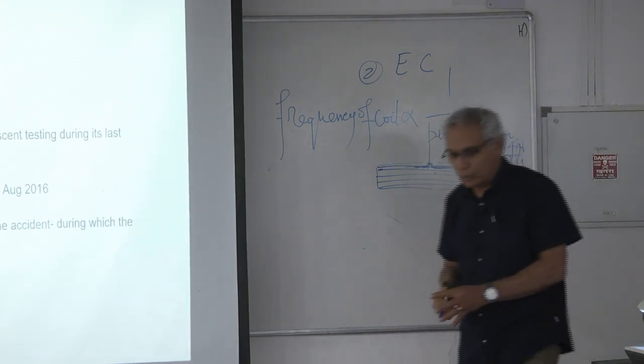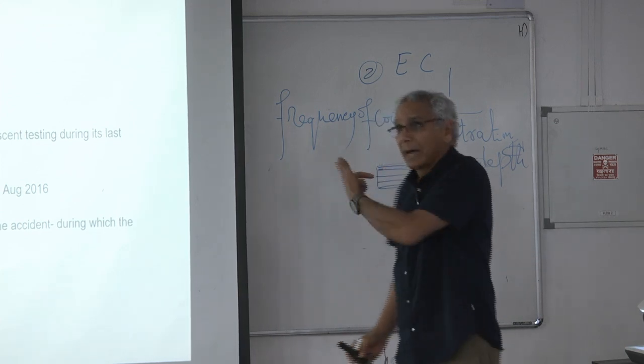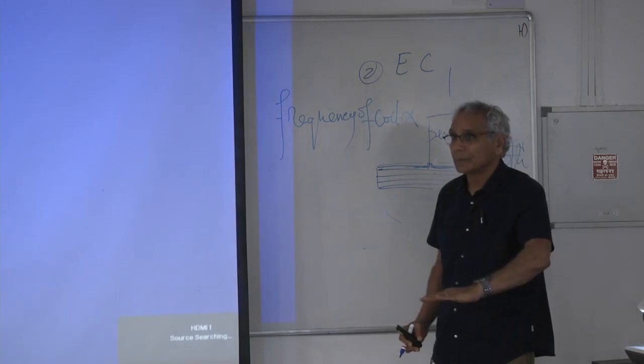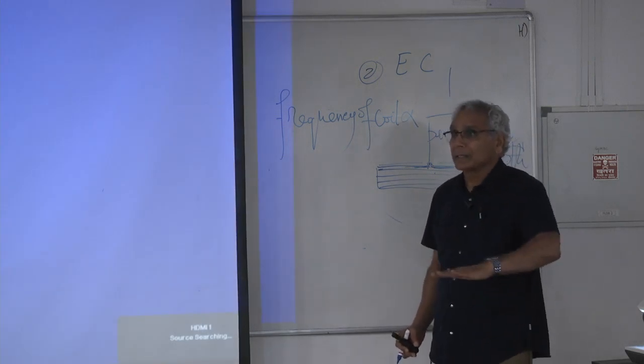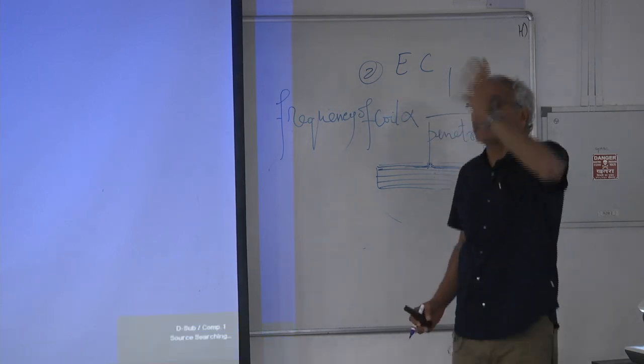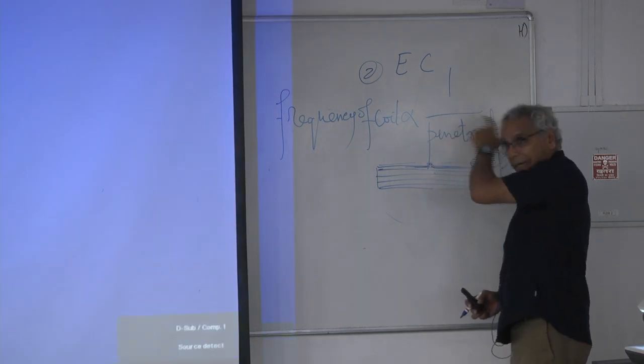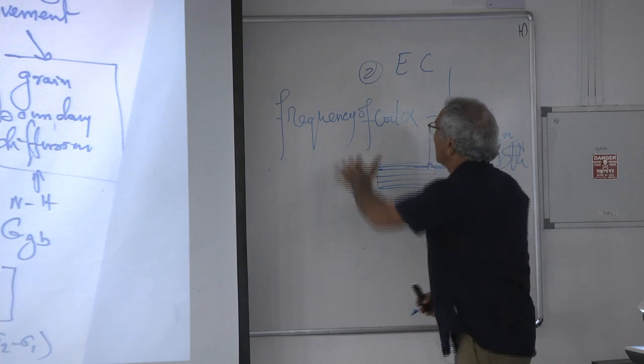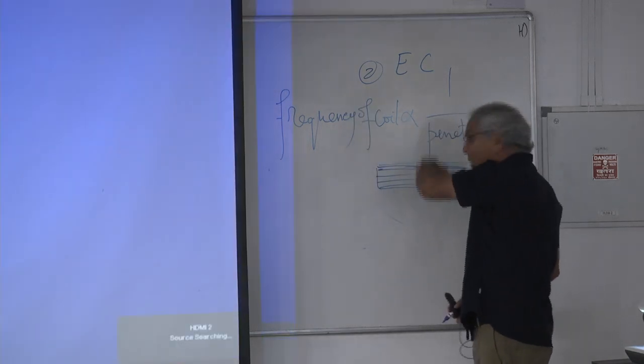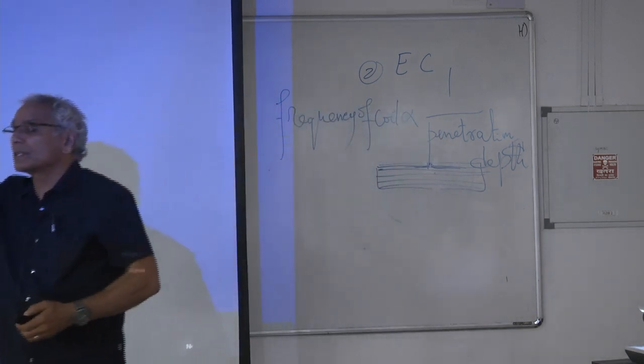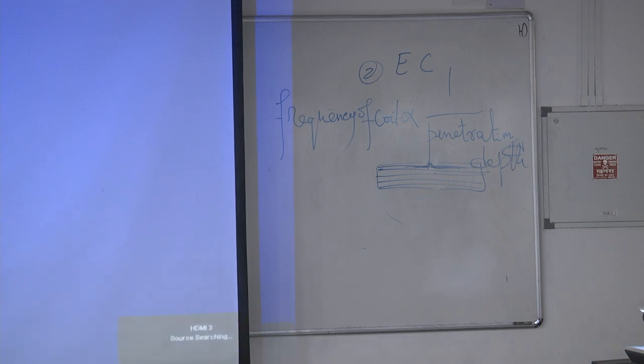If I'm looking for a crack on the surface, I use a high frequency because the penetration depth is low. So it becomes very sensitive at high frequency, and it will detect the crack on the surface. But if I want to go deeper, I reduce the frequency, and the electric field will go deeper. So the penetration depth is inverse of the frequency. The first thing you want to do with eddy current inspection is always use a low frequency coil and take a look at the forest from the helicopter, instead of looking at each tree. Then you increase the frequency and start looking at the flaws, because fatigue cracks always start at the surface.